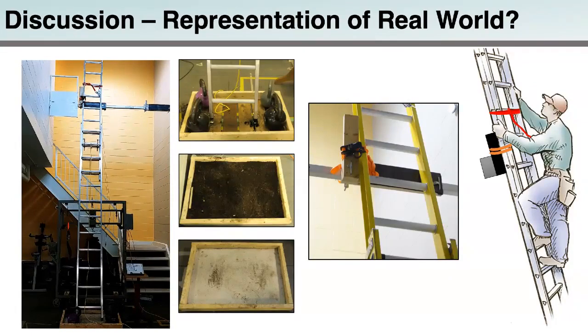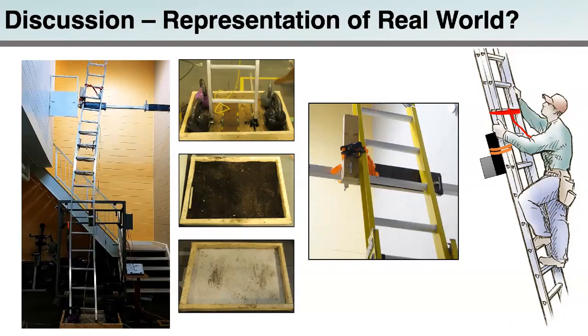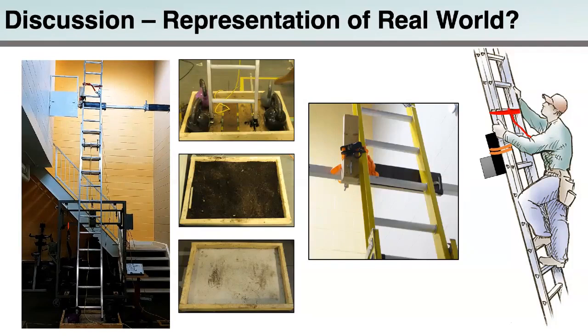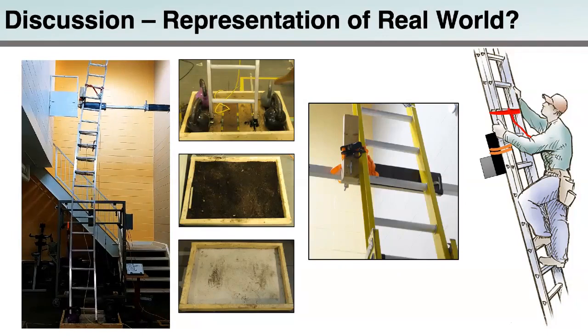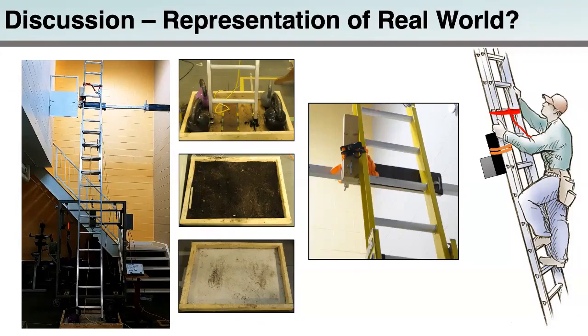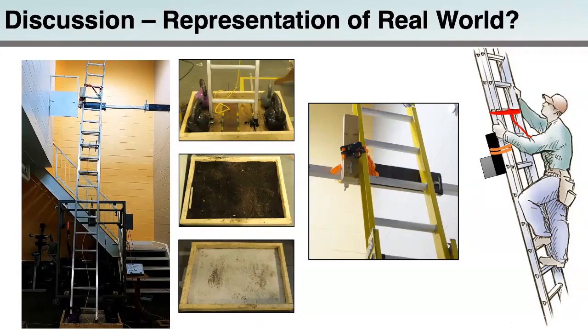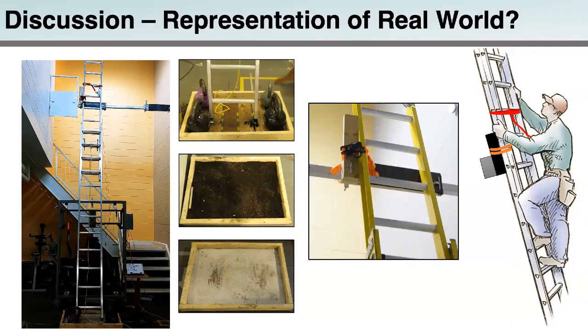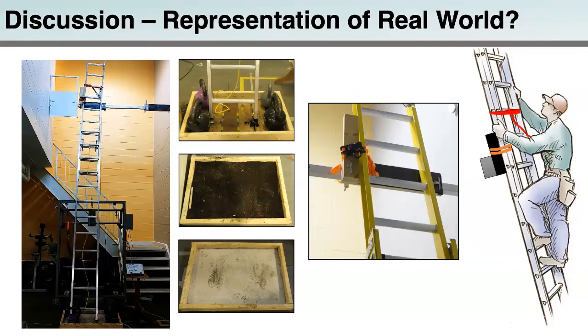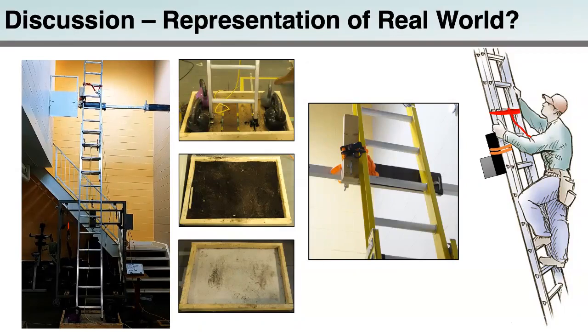When looking at the ground surface, this didn't seem to make a difference at all. And similarly for the leaning surface, we didn't observe any dramatic slippage during the drop test that would lead us to believe that one surface would perform better or worse than another. Similarly, the tethering method also didn't really appear to make much of a difference. As I mentioned, in the aluminum ladder we saw a failure with a rung tether tie-off method as well as a whale tether tie-off method. In terms of the fiberglass ladder, we really do think that rung failure was largely due to the cumulative impacts that ladder received.